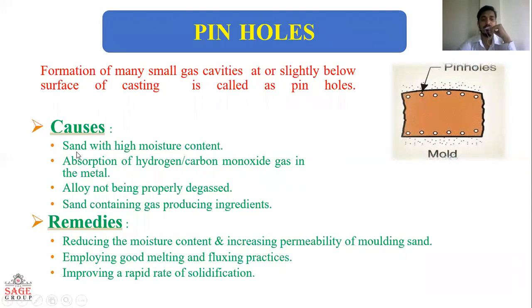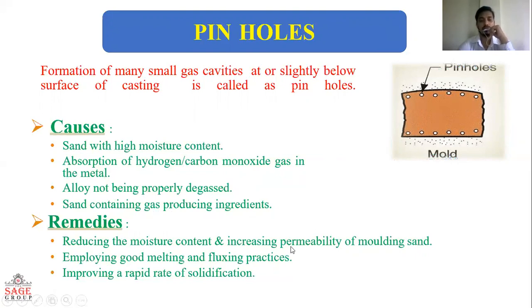Causes of pinholes: sand with high moisture content, absorption of hydrogen and carbon monoxide gases in the metal alloy not being properly degassed, and sand containing gas producing ingredients. Remedies: reduce moisture content, increase permeability of molding sand, employ good melting and fluxing practices, and improve rapid rate of solidification.